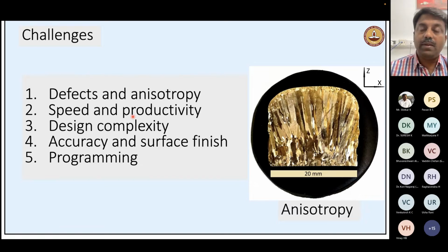If you look at the overall development for very specific components, for example a forging die, it takes about 3 months to make: starting from an initial casting process, then heat treatment to solutionize and anneal, then machining, final polishing and heat treatment, and then use. And that die would be used for hardly an hour. Otherwise, if you use it more than that, the die would collapse or crack. So we spend about 3 months to make the die, it works for 1 hour, and then it has to be completely scrapped. For such applications, additive manufacturing comes in very handy.